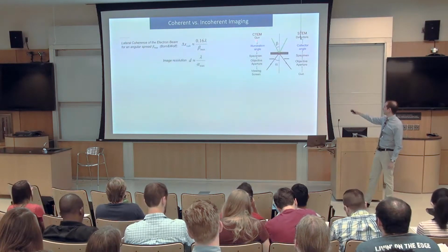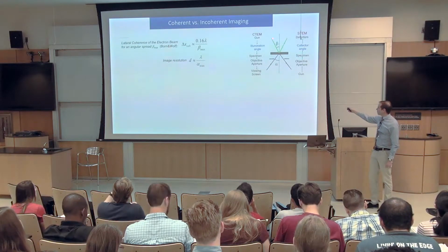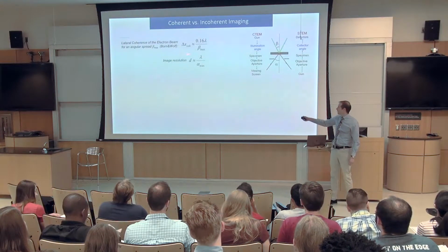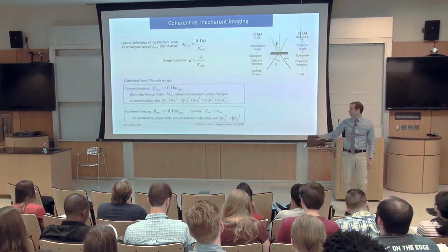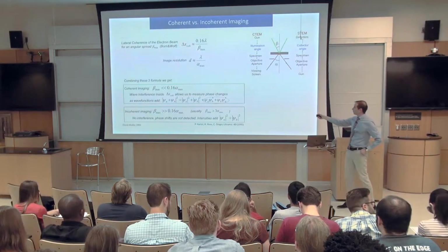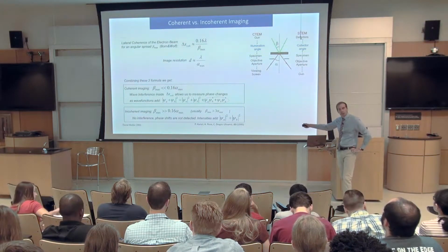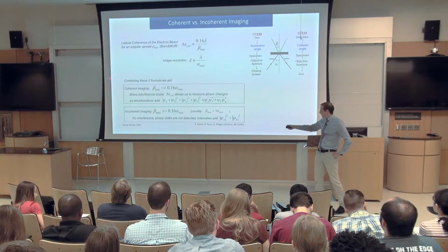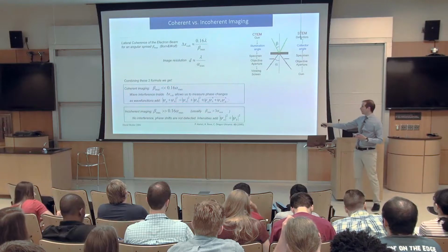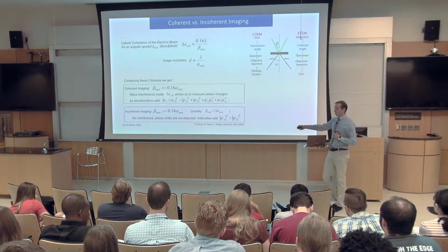We see a relationship between the illumination angle in TEM, the collector angle in STEM, and the term beta is measured relative to alpha. So we need to think about our coherence length in relation to the spacing in our specimen. So we can link these two equations and get a condition for coherent imaging where beta needs to be much smaller than alpha. If we have a coherent imaging condition, then all the waves that scatter will interfere with each other. That is to say, we have to take the amplitude squared of all of our wave functions.